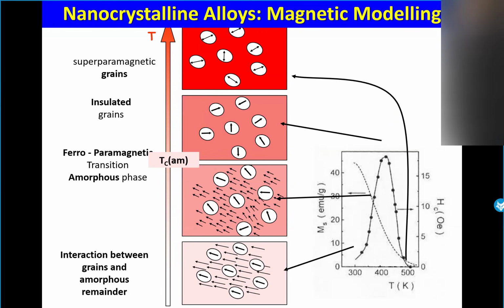When you increase the temperature, you will reduce the interaction within the amorphous matrix, which progressively becomes paramagnetic, completely or not. But what is important is that the coercive field will be zero when you have some superparamagnetic behavior of the crystalline grains.